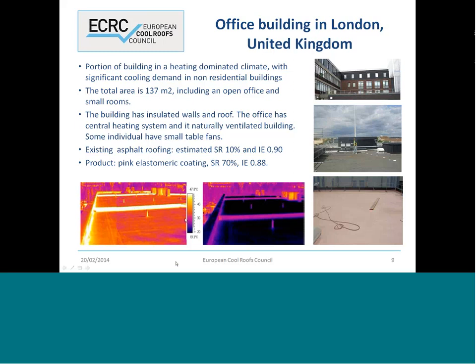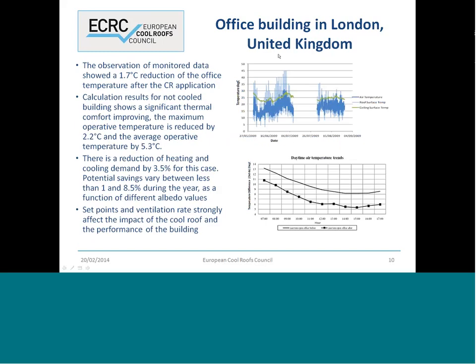If we look at the bar here, the absolute values of the difference are of course lower than those measured in Athens and Trapani, but we are here in a very different climate. Concerning the monitoring, it shows a reduction of the office temperature of 1.7 degrees after the cool roof application. And after the monitoring, an extended calculation campaign led to relevant results. For the not cooled building configuration, the thermal comfort was improved, since the maximum operative temperature is reduced by 2.2 degrees, while the average operative temperature during the summer period by 5.3 degrees.